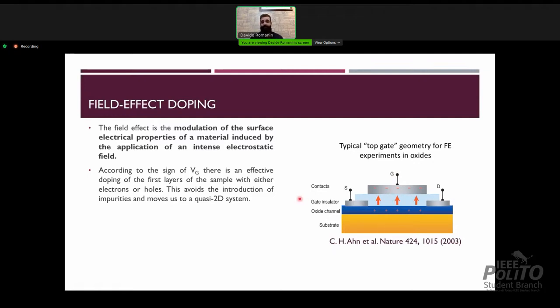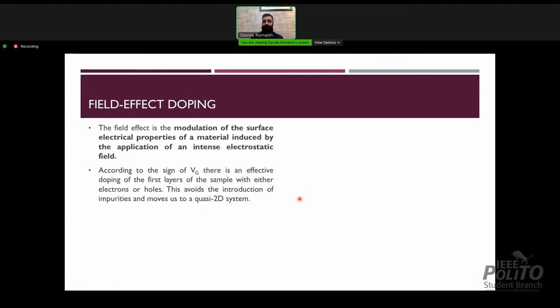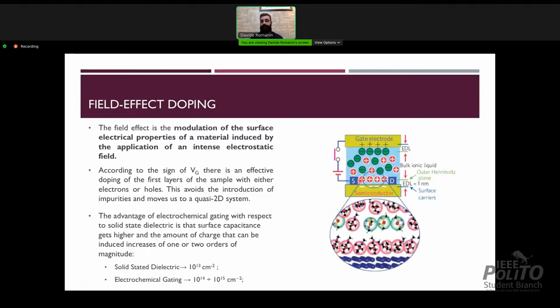Moreover, if instead of a solid dielectric, we use a liquid or a gel electrolyte, we can exploit the formation of an EDL, an electric double layer, at the interface between the electrolyte and the material, which acts as a nanocapacitor. Therefore, the electric field becomes very high in magnitude, and we can achieve induced charges, which are one or two orders of magnitude higher than solid state dielectric devices.